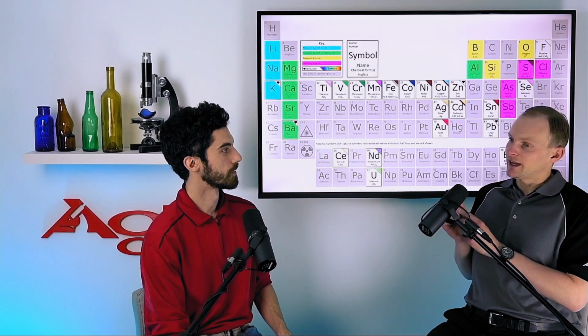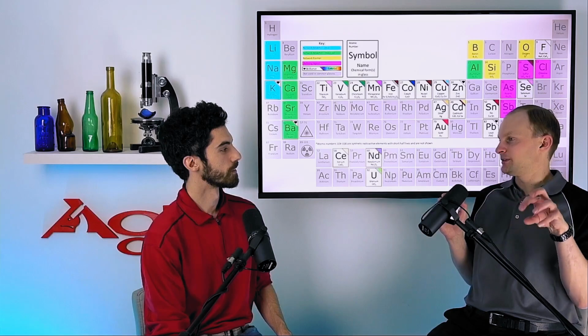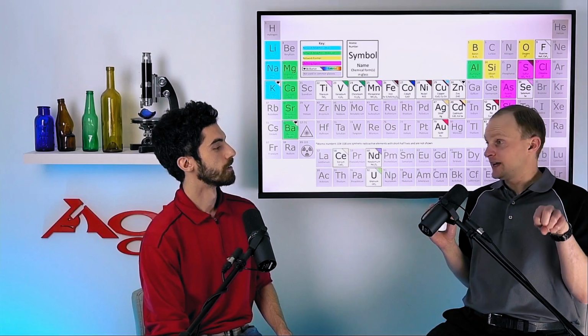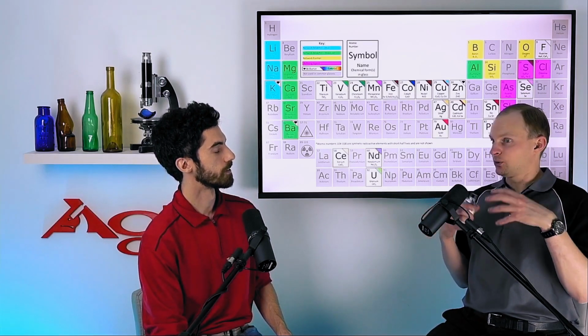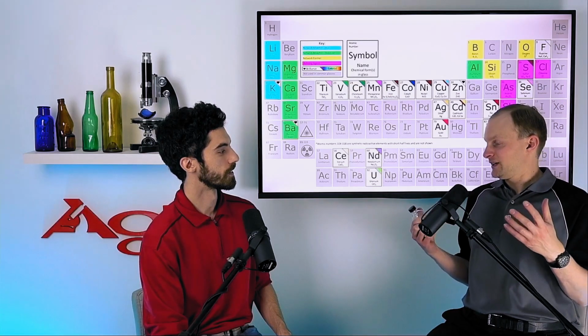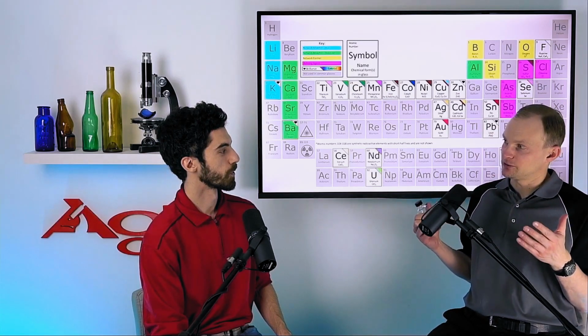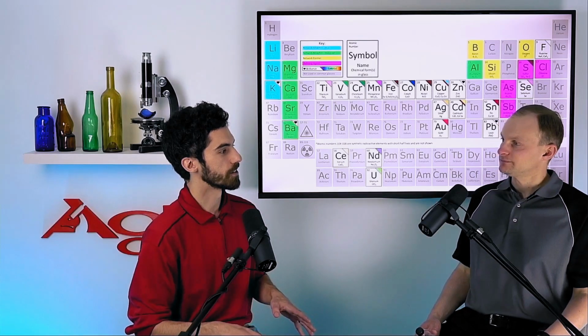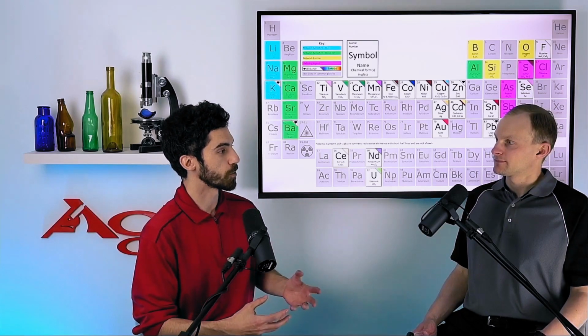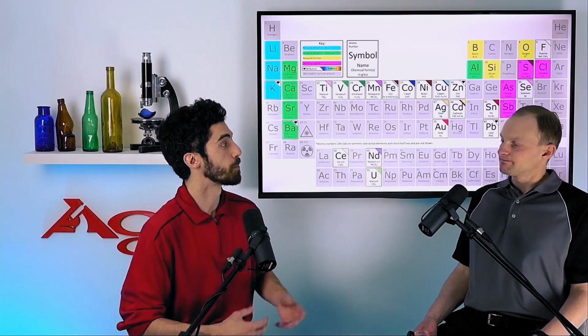But soda ash, that sodium, it actually lowers that melting point. It acts like a flux. And so now we can make glass in ordinary fires and furnaces that people in ancient times could get those temperatures. So the whole reason why we're adding this to the glass isn't because it's a necessary component for glass itself. It just makes the process that much easier, maybe more energy efficient.